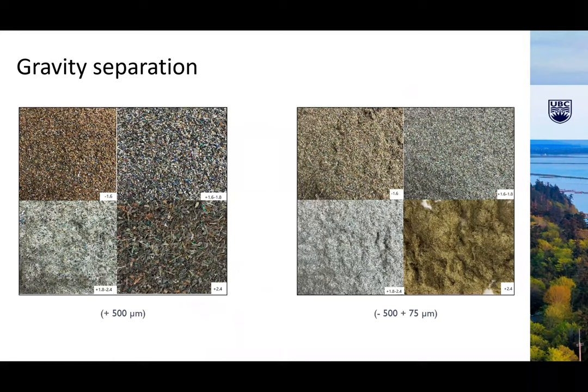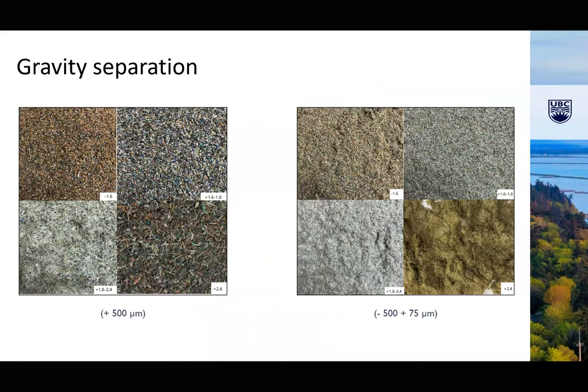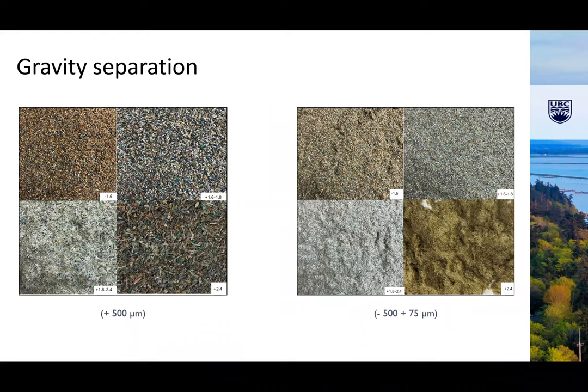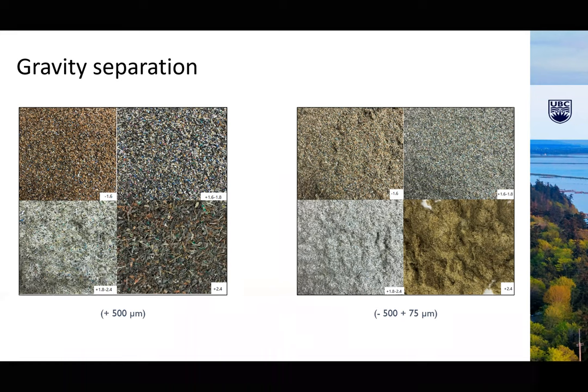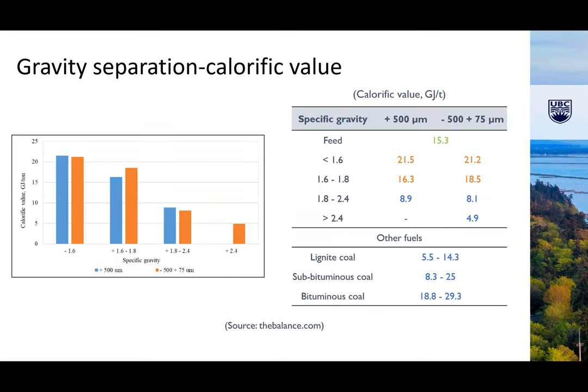So when we look at the materials physically, you can see right away that the different particles ended up in different fractions. Not surprisingly, the heaviest were the metals. 2.4 SG is the fraction where it holds all the strings of copper and other metals. Fiberglass, the 1.8 to 2.4, and then plastic in the lighter fractions, which is not unexpected. But you can see right away that the quality of material is much different in each gravity fraction. Looking at the calorific value, we've already seen that by separating the metals, we increase the calorific value in our non-metal fraction.